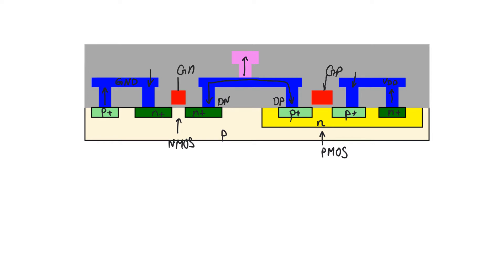When we think about how we created this, we created it in layers — each mask was used to create all the features on a certain level of the wafer. The order in which we made the layers is a little different from how they are arranged bottom to top, but more or less follows the same logic. We start with the well using diffusion, then created the field oxide and thin oxide, then the polysilicon gates using chemical vapor deposition, then used the p-plus mask to create p-plus areas, the n-plus mask to create n-plus areas, then a mask to create contacts between metal one and diffusion and polysilicon, and then deposited metal one.